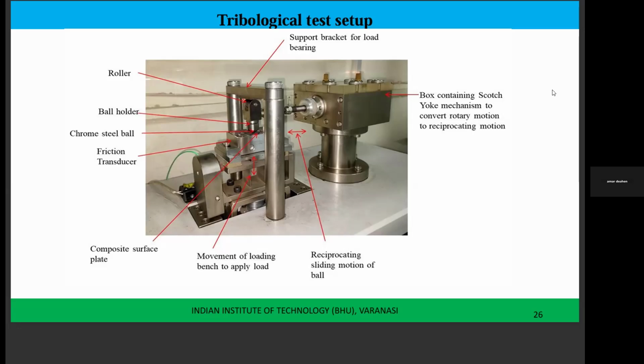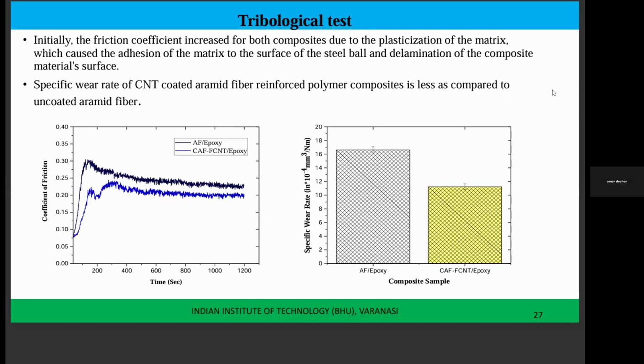Next slide, please. You can see that the friction coefficient initially increases for both the composites because of the plasticization of the matrix. This is due to adhesion of the matrix, and in some regions abrasion is also possible, and delamination of the composite material surface. For specific wear rate, you can see that for the coated one, it is reduced compared to the uncoated one.